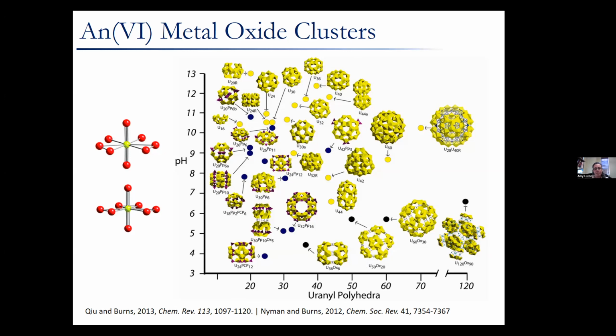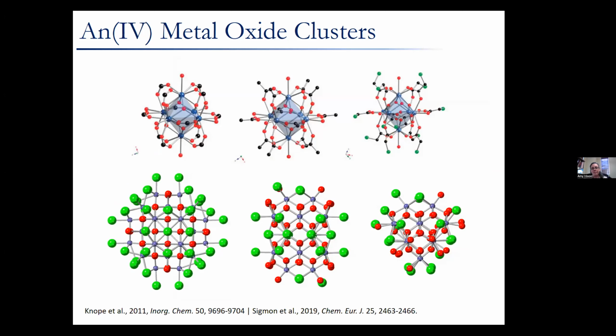More recently, though, we've been shifting to the lower valence states, so focusing on actinides in the plus four oxidation state and the metal oxide clusters that can form for them. At the top of the screen is the well-characterized hexanuclear species. That means there's six actinide metal centers that are bridged by oxygen atoms, and in this case are often capped with organic ligands. And this hexamer has been identified for a number of the actinide elements from thorium, uranium, neptunium, and plutonium, at the very least.